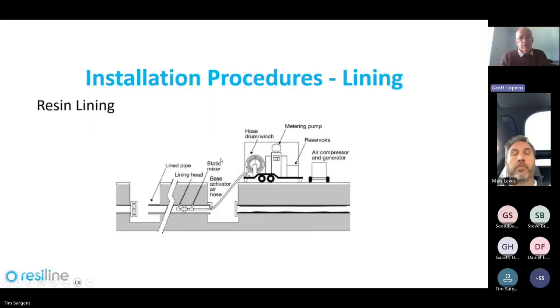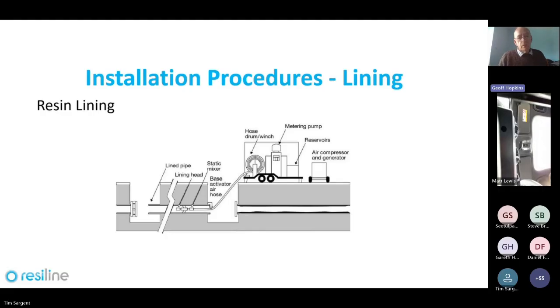Okay, next slide, please. The actual lining process. The lining process in itself is you will clean the pipe and CCTV it, as we've just discussed. When you're ready, while your cleaning work is going on, you would precondition your lining rig, and I'll talk about that a little bit more later. But assuming your lining rigs are ready to go and your material components are all up to temperature, you would pull the umbilical lining hose through to the far end. So you've got 2 pits. You're working from an open pit to an open pit. You will pull the umbilical hose off the lining rig all the way through to the far end, and